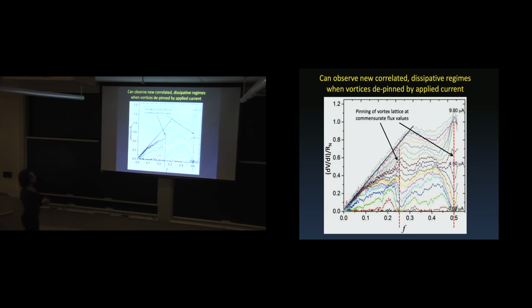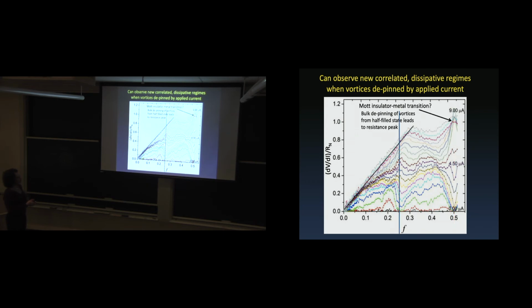So you can see a couple things. Like I said, you can see the pinning at commensurate vortex lattices. Here's at a quarter, here's at a half. At a half filling, you get this dip to peak behavior. That's something pretty interesting because you're just increasing current, and it goes directly from a superconducting dip to a peak in resistance, which has been associated with a Mott-insulator transition before.